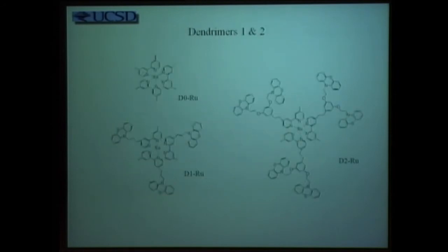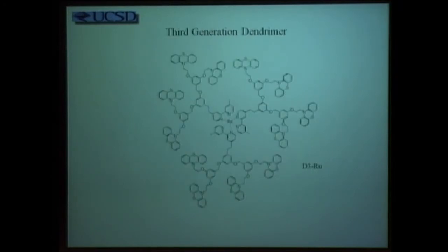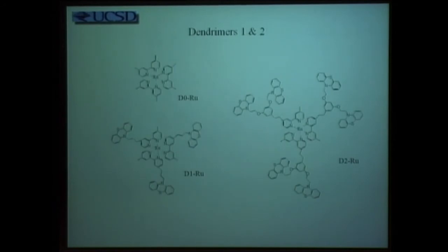There's another way that you can do that, and that's by building up molecules around a central core, what is called dendrimers. So we here have a dendrimer in which the first material, this first substrate shown at your top left, I think it's ruthenium. I can't see very well. It's ruthenium trisbipy. Ruthenium trisbipy, and then what we've done is replaced by substitution on one of the bipyridyl rings once, twice, three times. So this is a group that has three times as much as the absorption on the outside.